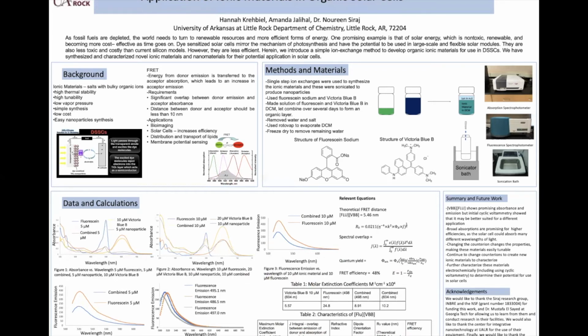In summary, our ionic material shows promising photophysical characteristics. However, when we conducted cyclic voltammetry, we decided that it may be better suited for a different application because in order for it to be used in a solar cell, it has to have high oxidation and reduction potentials, which it has not shown so far. However, it is showing broad absorption, which is good for higher efficiencies in solar cells as it could absorb at different wavelengths of light. In the future, we hope to continue to characterize it and then change the counterion in order to explore future dye pairs and then synthesize and characterize those.